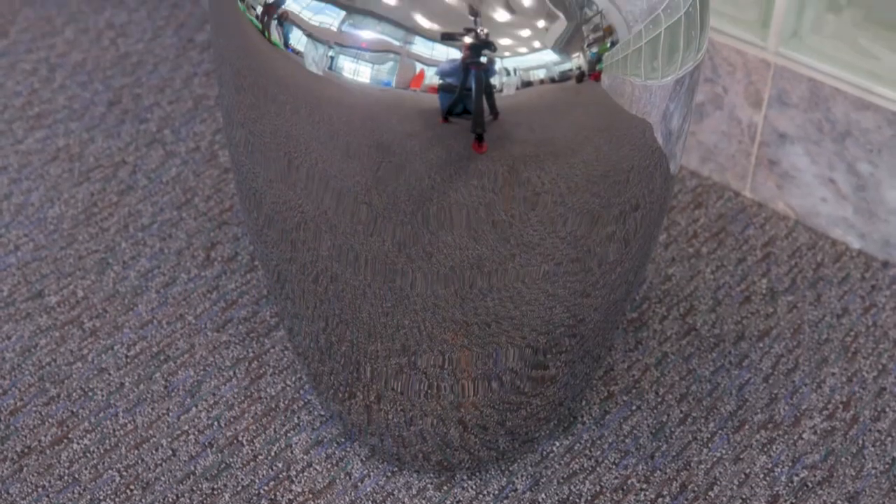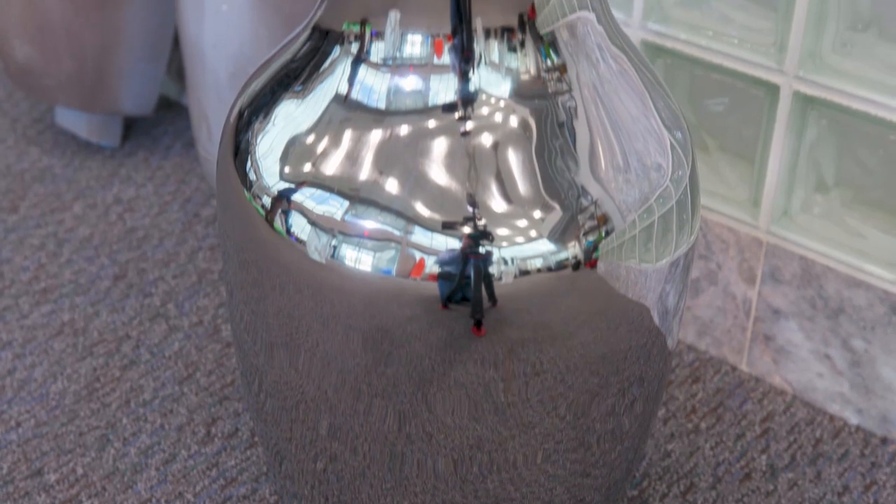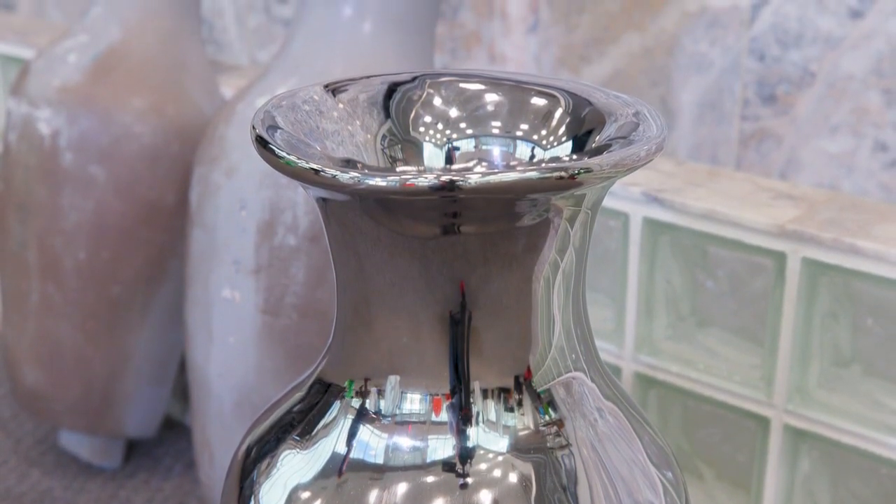And then they were packed in sand, removed, the two cavities were put together, and then they cast it in stainless steel. This is a pattern shop and foundry in Morelia, Mexico that is using the pellet extrusion 3D printer.